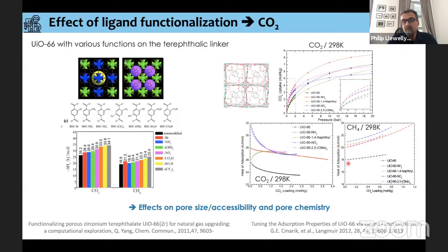We can also see that there are variations depending on the various linkers that they've put into the material. So to cut a long story short, what we see here is that the linkers have an effect on the chemistry. We can see here for the CO2 different interactions, but also on the pore size and maybe the accessibility of some of these pores to these probe molecules. So the effect of ligand functionalization is not as simple as one could expect.